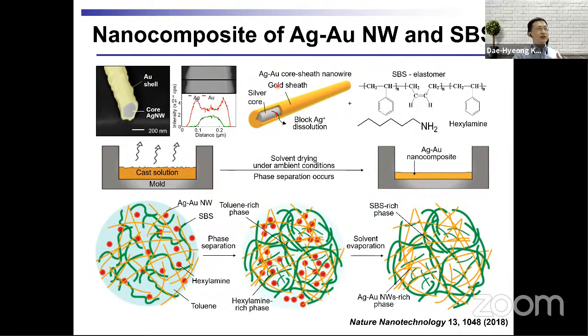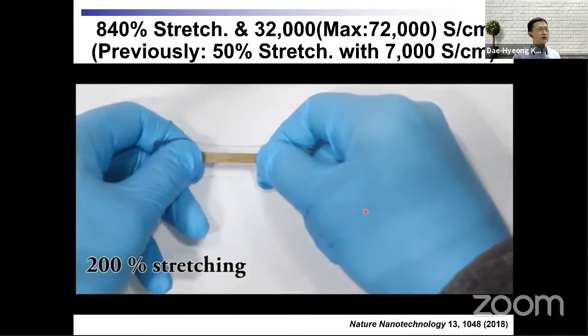But instead of using bare silver nanowire, in this case, we coated the surface seamlessly with a gold shell. Then, since the gold shell is inert, the oxidation of silver nanowire can be prevented, and also silver nanowire dissolution can be prevented. So we could solve the oxidation issue as well as the biocompatibility issue. In addition, we optimized the polymerization conditions, such as the polymerization temperature or additive amount, to induce local microscale segregation. So we could achieve high conductivity and stretchability because of that special structure.